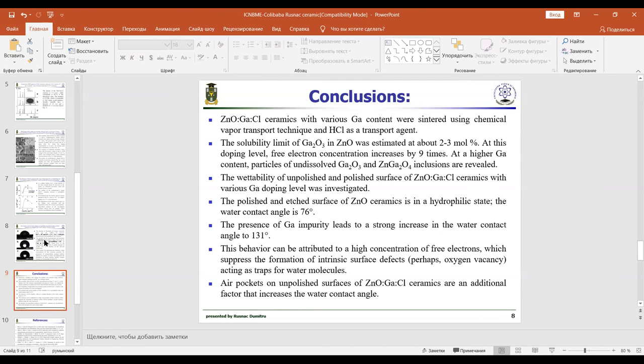Wettability of the polished and etched surface of zinc oxide gallium chloride ceramics with various gallium doping level was investigated. The polished and etched surface of zinc oxide ceramics is in a hydrophilic state. The water contact angle is 76 degrees.